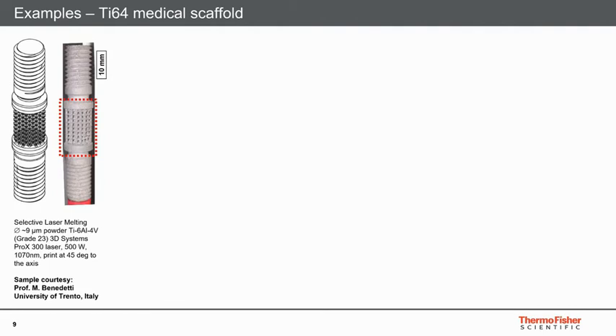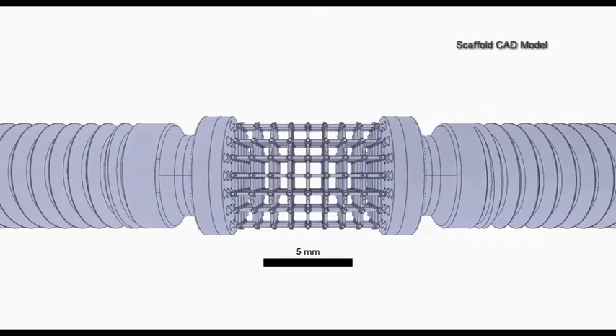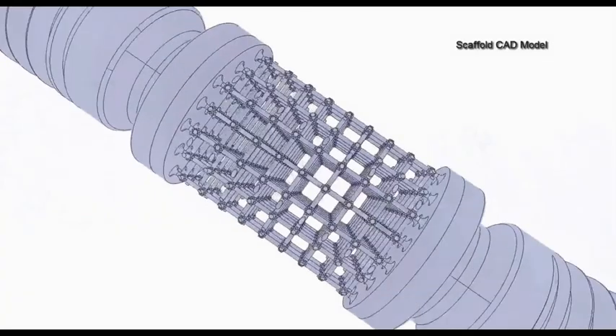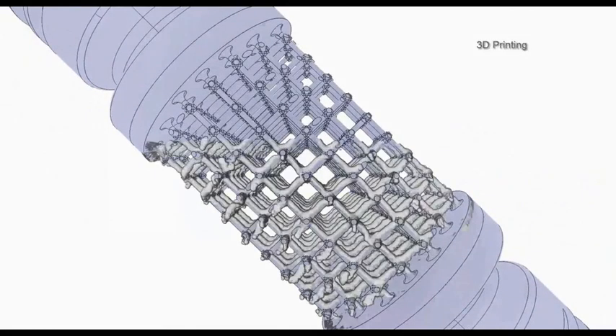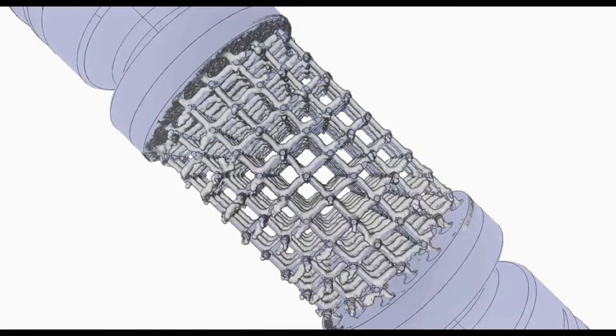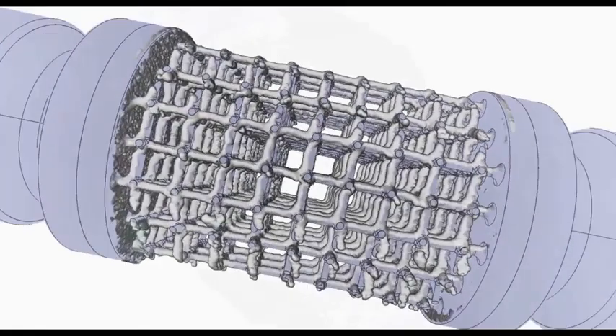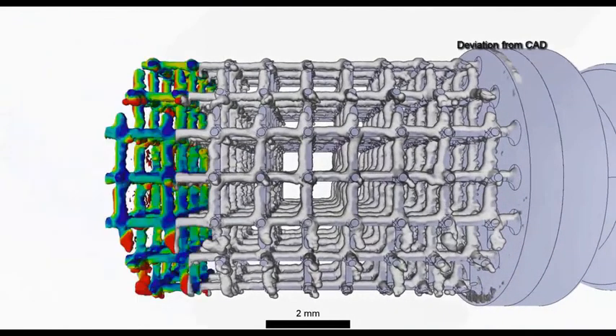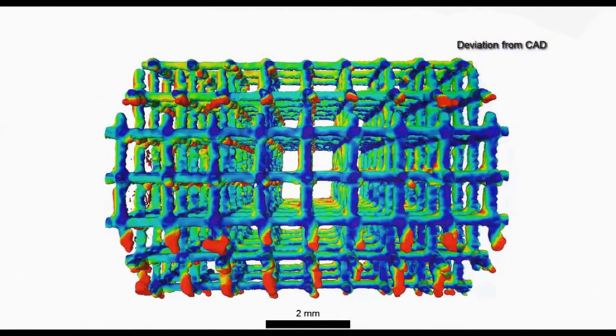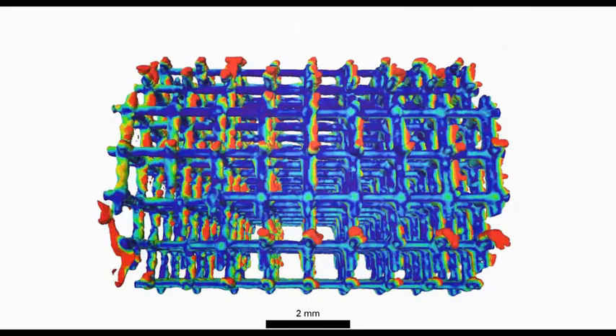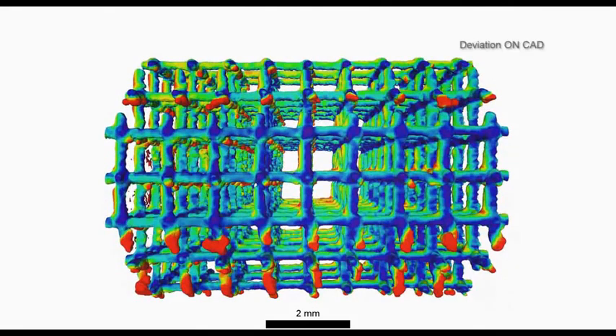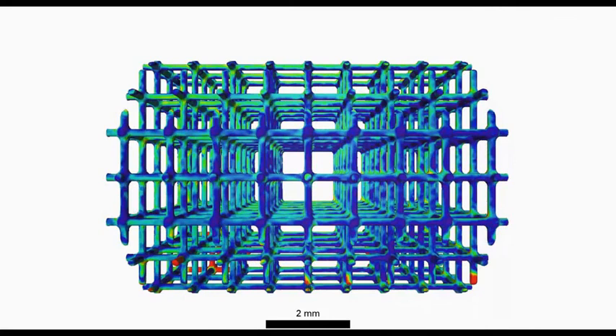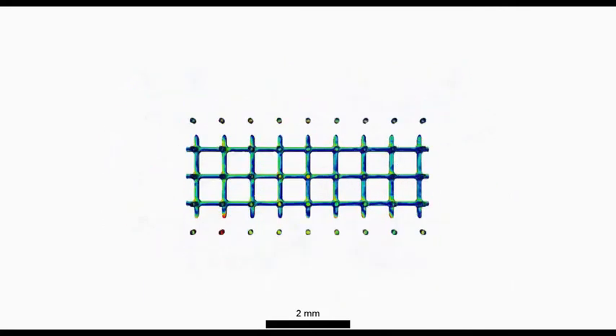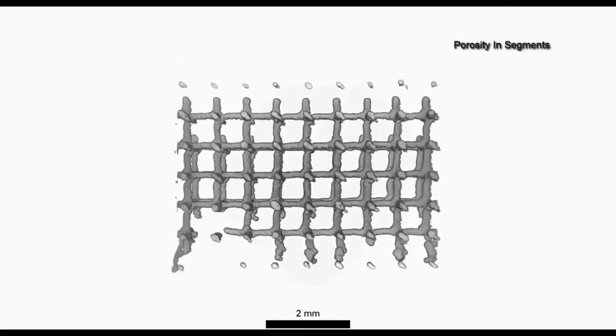Here is the second example of a Ti-64 medical scaffold. This build is designed for fatigue testing. Using correlative microscopy, we analyzed the as-built sample. We can see geometric deviation of the build from the CAD model. We can analyze porosity, quality of the build, and distribution of thicknesses of the struts.